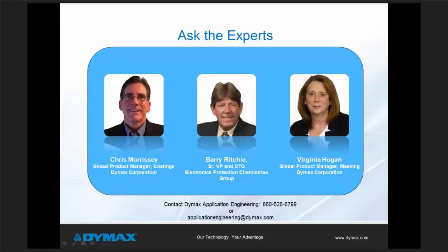Yeah, Lori, thanks. That is actually a good question, because with secondary moisture cure materials, it's best to recoat or rework the boards as soon as you can. After the secondary moisture cure takes place, there is a polarity change on the surface of the material, so on the surface of the board. So it can be more difficult to bond to. So you do have to test that, but in general, if you have to apply additional material or rework the board, the earlier you do that before full moisture cure is better. You can also apply other conformal coatings to those surface areas, and they will bond to the secondary moisture cure conformal coating. So that's another alternative that can be used.